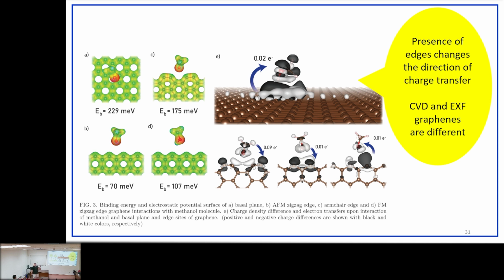So I'm showing calculations for the zigzag edge two times because, you know, for graphene, you can have ferromagnetic edges or antiferromagnetic edges. If you are performing your experiment at room temperature, you can have both of them. This is why, to not miss this scenario, so to make it complete, I calculated for the AFM and ferromagnetic cases. But they are not that different, so the binding energy is still high. And this part is important.